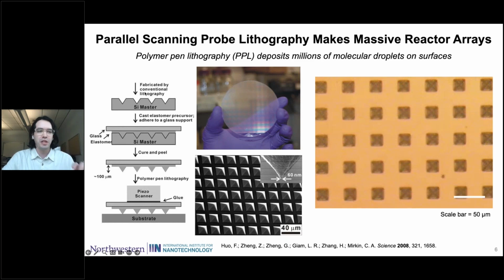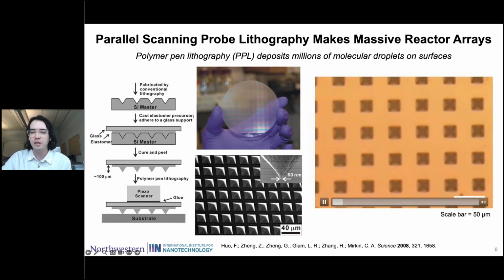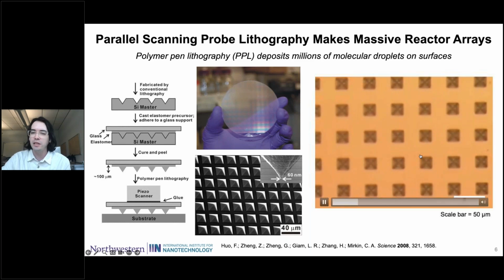So, more specifics on what this actually looks like. We first use standard lithography techniques with silicon wafers and elastomers coated onto them, so we can construct these arrays of pen tips. You can see at the wafer scale, we can generate large amounts of pen tips, and then zooming in, each one is a pyramidal shaped pen where the tip is now at the tens of nanometers dimensions.